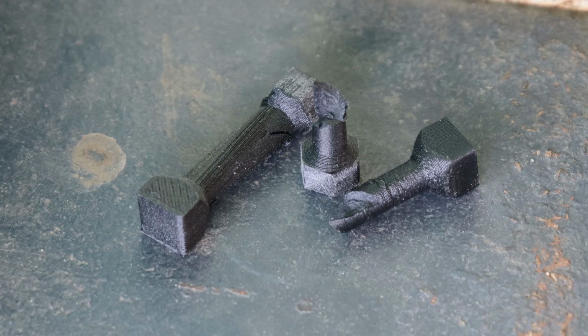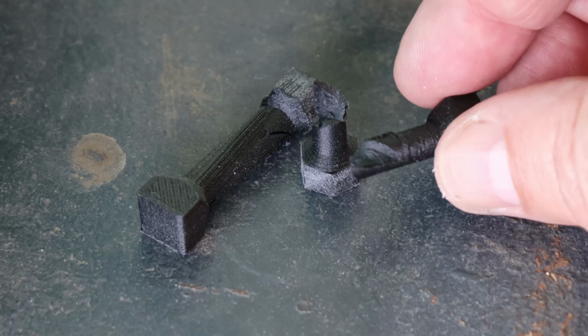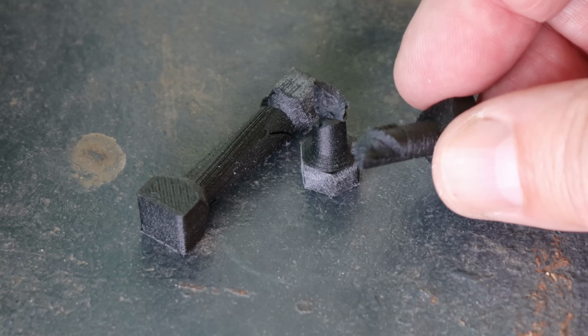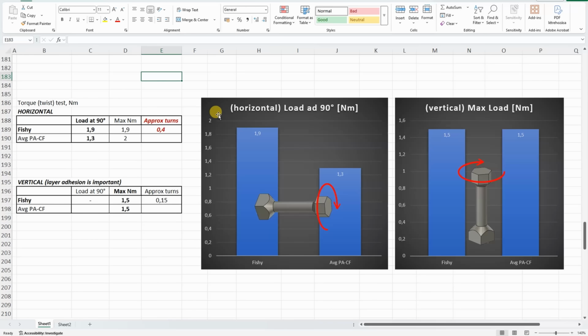1.9. With vertical objects, this is an interesting break when it's not along one layer. Printed in horizontal position, load at 90-degree rotation is significantly bigger compared to the average PACF. Printed in vertical position, the values are very similar, but what I like with the fishy filament is that cross-section, which is not along the one layer.